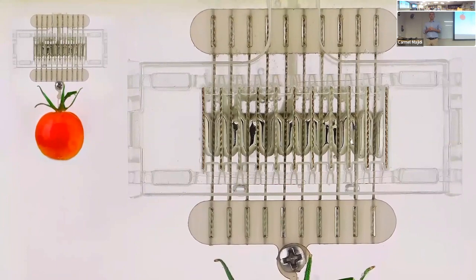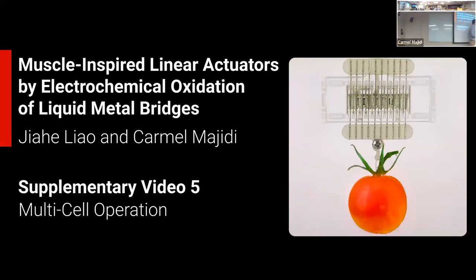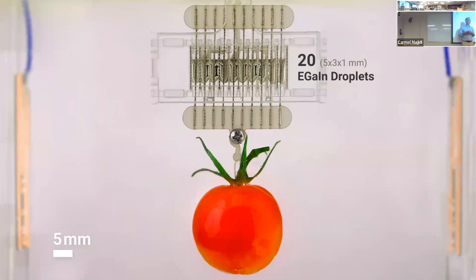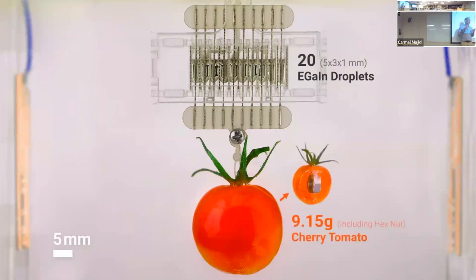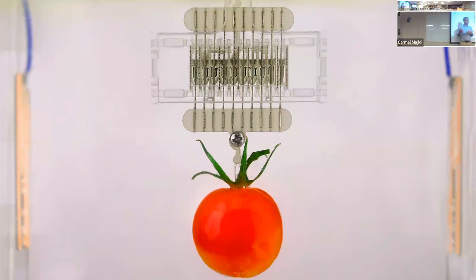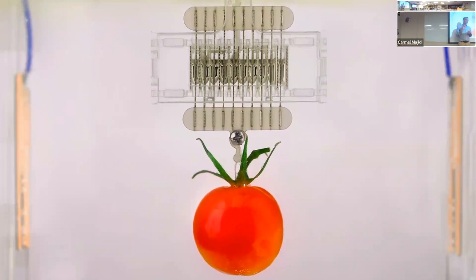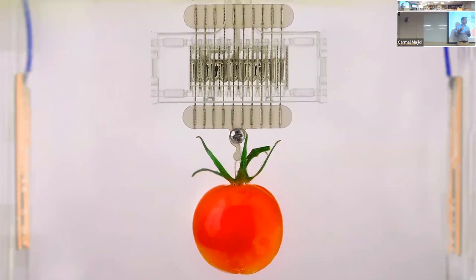Lots of bubbles rising. Yeah, so to get in the reduced state, we have to play around with the pH. We're using potassium hydroxide. The problem is we have an aqueous solution of potassium hydroxide, so there's electrolysis going on. Even though the voltages are low, they're still just high enough that hydrogen and oxygen bubbles are forming. So that's what you see there.